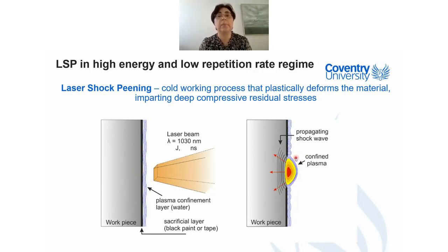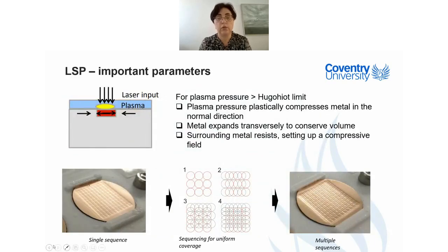And this process plastically deforms material and imprints deep compressive residual stress. When I say deep, we are speaking about more than millimeters. How that looks: you have your workpiece, then you put a so-called sacrificial layer. Here is the black tape, usually a vinyl one. This tape has two roles: to protect your workpiece from heating and also to be ablated and create the plasma.